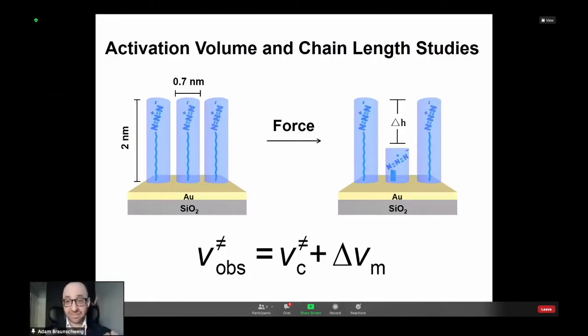What we did was we imagined that our azides don't act in isolation, but they're tethered to the surface by these chains. And when you push on the azide, you're also pushing on the chains below them. So the observed activation volume is going to be the activation volume of the cycloaddition plus whatever change in volume that you have of the underlying layer. So you have to consider the whole system. So this led us to hypothesize that the activation volume measured is going to be a function of the chain length of the underlying monolayer between the gold and the azide.